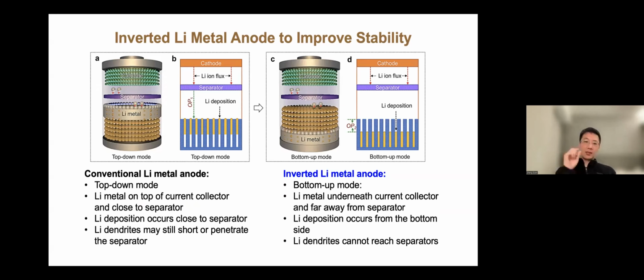But instead of putting our lithium metal next to the separator, we flip it around, right? So then at this point, the lithium metal is away from the separator, and in the middle, there's a spacer made of this highly porous, three-dimensional conductive textiles.